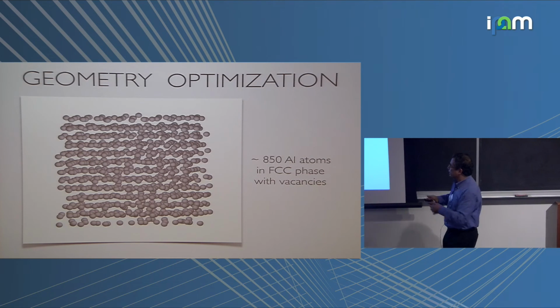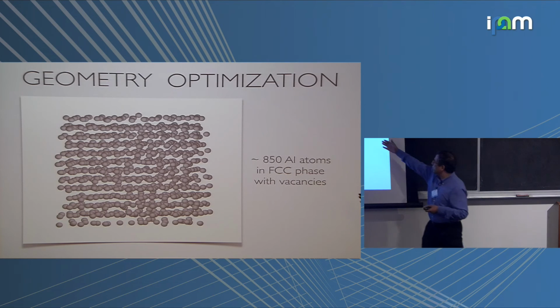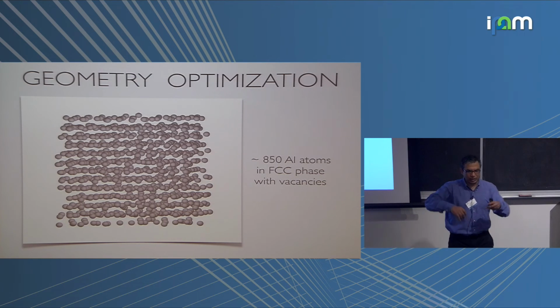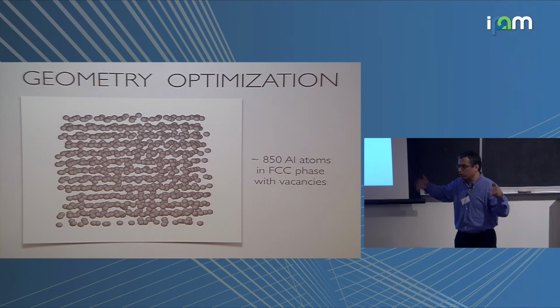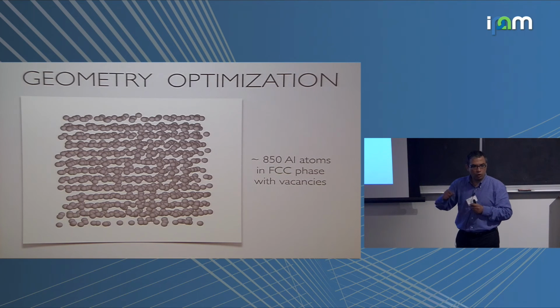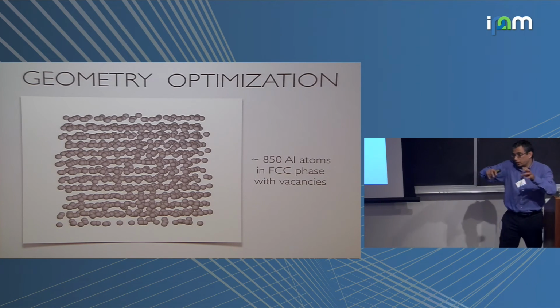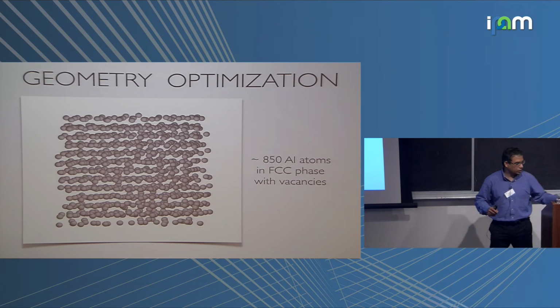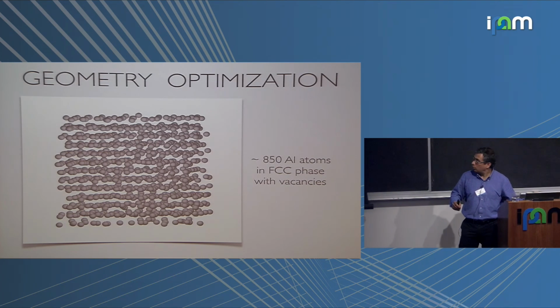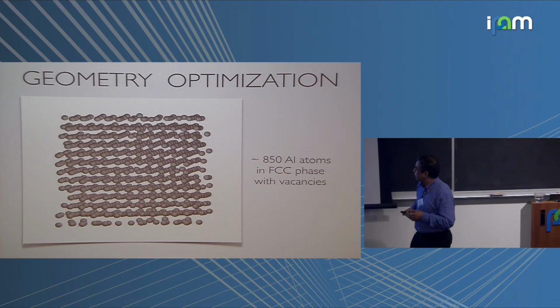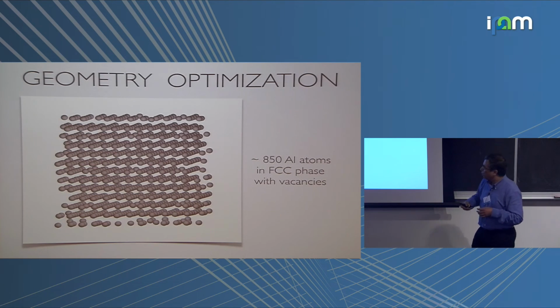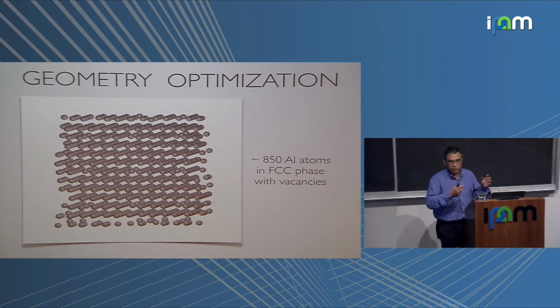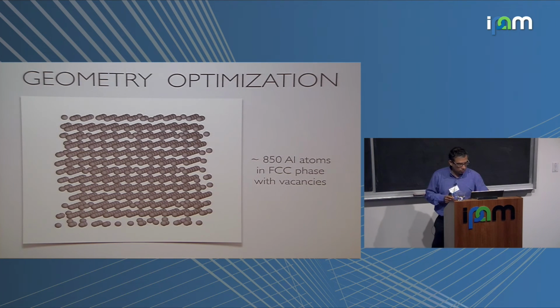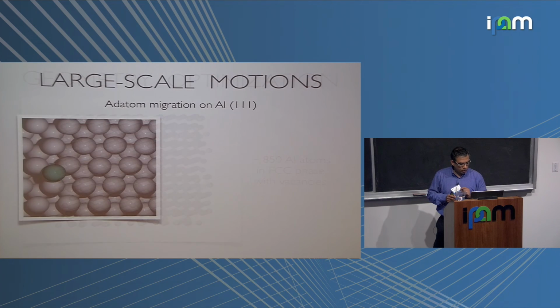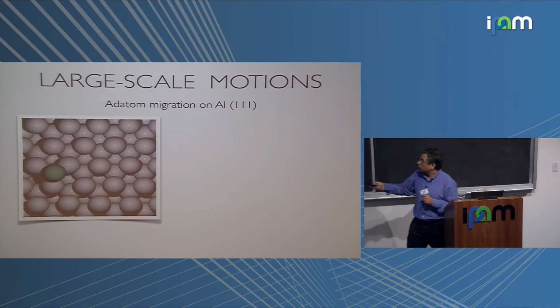Here is an example where we considered a large unit cell of aluminum, 800 or so atoms, that contains vacancies as well, and then we randomly perturb all the atoms. We wanted to know if our force field can be used for a simple geometry optimization exercise. The force field computes the forces on the atoms, and then you minimize the forces. Is it able to do a geometry optimization? Here is a simulation of the geometry optimization process, and it seems to do pretty good.